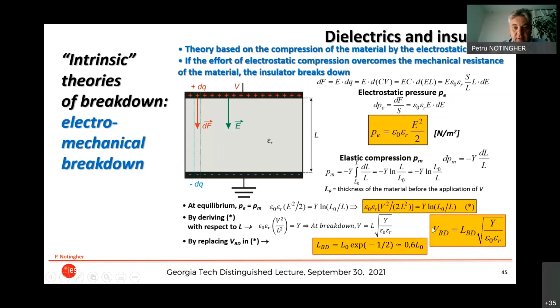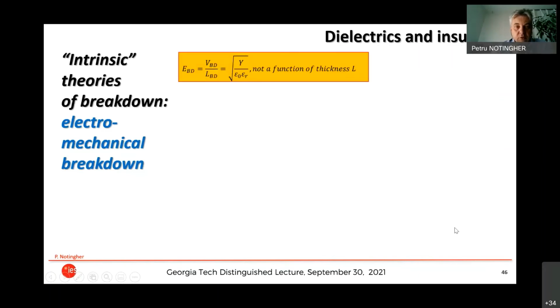If you make the calculation, you will find that the breakdown voltage depends on the thickness and also on the Young modulus and on the permittivity. And of course, if you divide everything by L_BD, you will find that the breakdown field is not a function of thickness. So it's a function of the Young modulus and is inversely proportional to the square root of epsilon r.